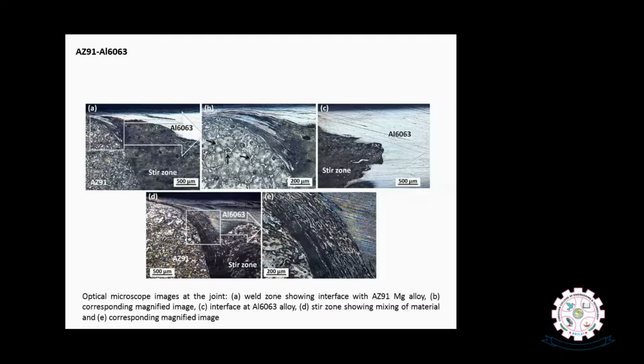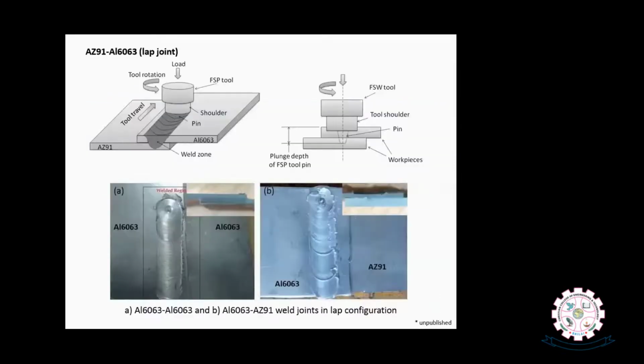However, in the bottom magnified images, you can see some metallurgical continuity between both alloys, magnesium and aluminum, in the nugget zone. So therefore, dissimilar magnesium aluminum joints usually appear with a combination of metallurgical continuity as well as mechanical mixing of the material. Together, these two factors help us to develop a sound weld joint.